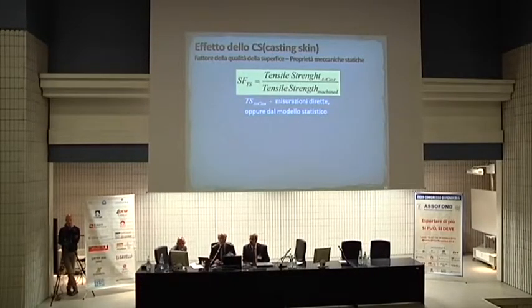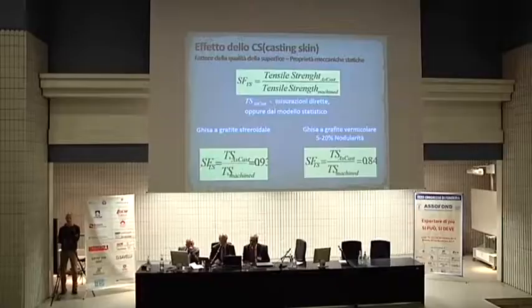And so we always want to put numbers and quantify any effect. We defined what we call a casting skin factor, which is simply the ratio between the tensile strength of the as cast sample and the tensile strength of the machined sample. So it's always smaller than 1. When it's 1, that means we have no effect. And to give you 2 examples, for spheroidal graphite cast iron, this casting skin factor for our experiments was 0.93, and for compacted graphite cast iron, it was much lower, 0.84, and I'll explain why. So compacted graphite cast iron is affected more by the mold than ductile iron.